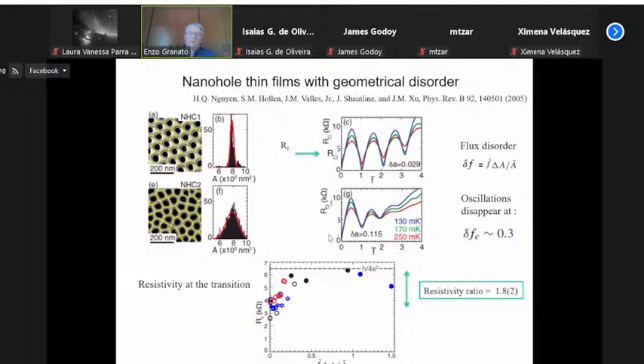Now, if you look at the resistivity at the transition, with the crossing points, as a function of this disorder parameter, you see that the resistivity for a small disorder is close to the value of the sample without disorder, of course. But as you increase the disorder, it increases until it saturates at some particular value. So there seems to be a dependence on the disorder, and eventually it saturates. The ratio between the saturated value and the value at zero field is around 1.8. So this data motivates us to look at modifications of the model which would describe this experimental data.